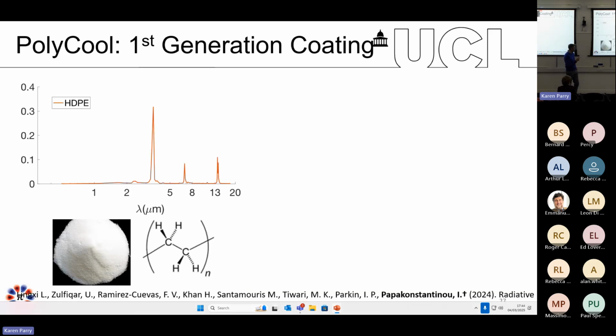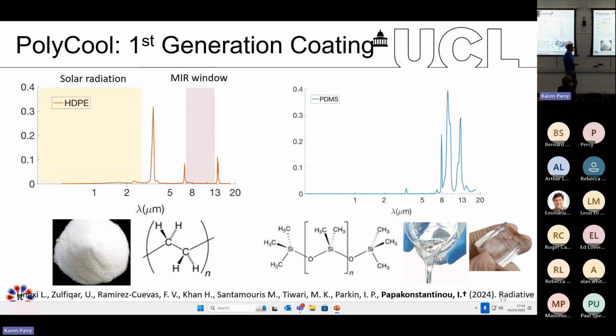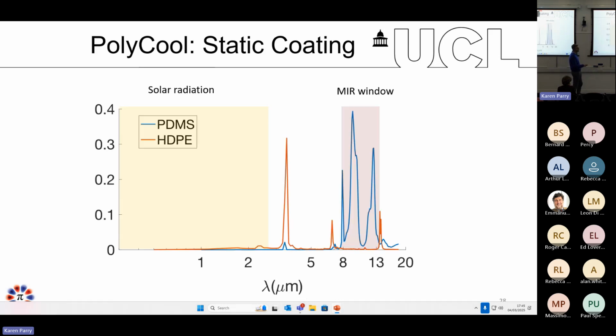So the first generation of coatings that we have developed uses polyethylene combined with polydimethylsiloxane. The reason why we use these two organic components is because polyethylene is a very inert material. These are, by the way, the FTIR peaks, the absorption peaks of the organic compounds that we use in our system. It has zero absorption in the solar spectrum and in the MIR window, whereas PDMS concentrates all its heat emission within the MIR window. So if you combine the two as a system, you have nearly ideal conditions for radiative cooling.